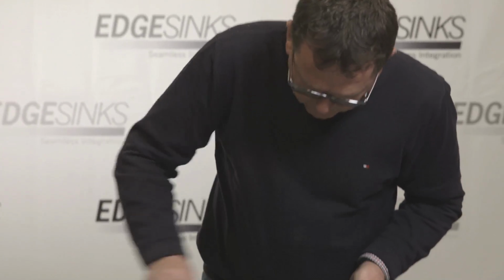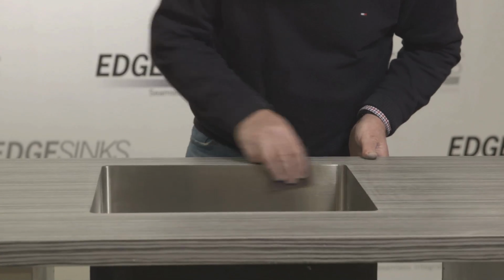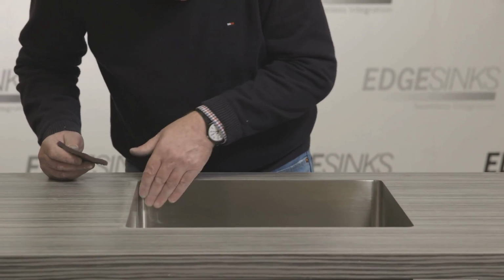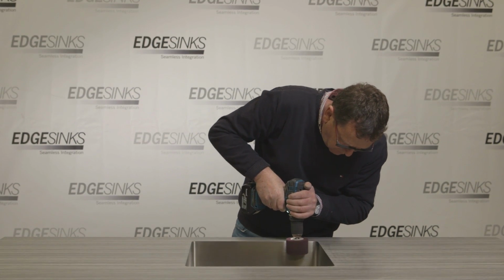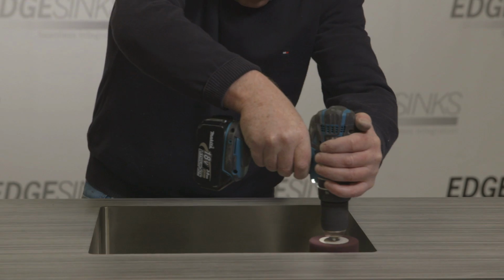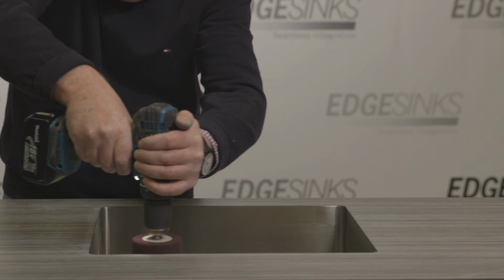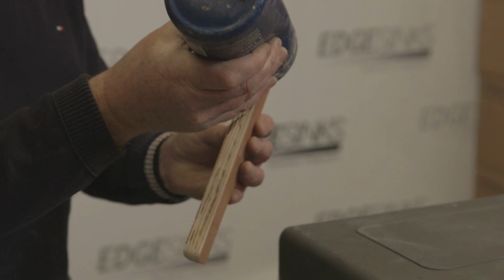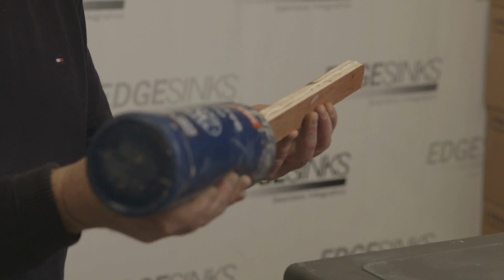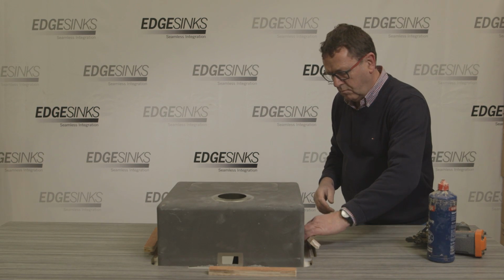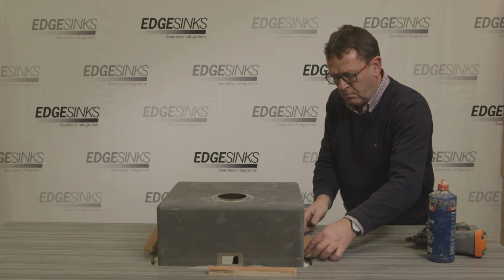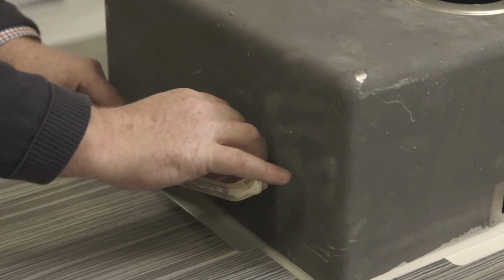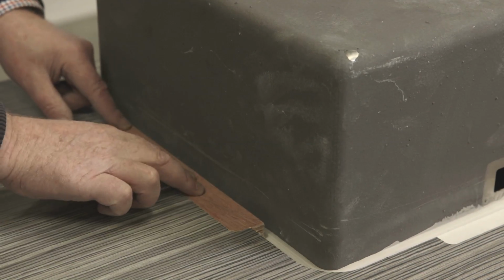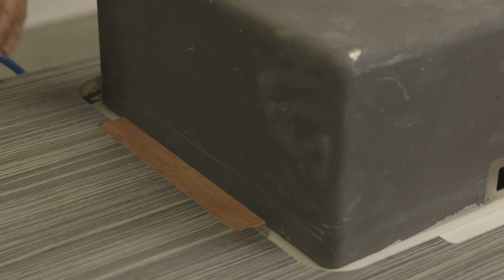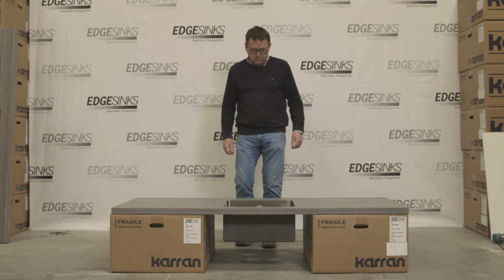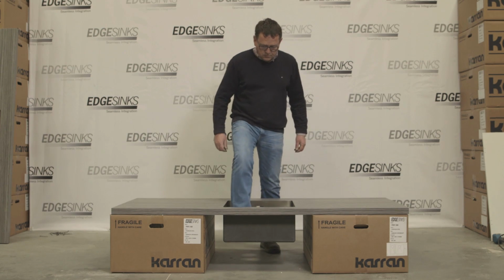If you mark or scratch the sink wall when sanding, use a 3M maroon Scotch-Brite pad or a 180 grit flap wheel to repair it, always running straight and parallel with the brush of the steel. We recommend additional under support for the sink. There are various options. In this case, we have machined an extra step in the back of the worktop to incorporate plywood cleats which can be glued and pinned in position to give that extra support to the sink.